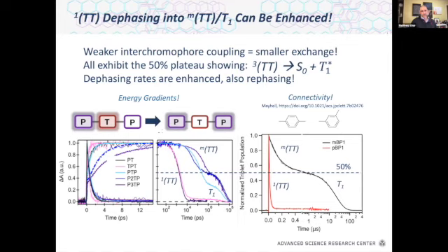But if you just deuterate the crap out of everything. Yeah, we tried with the deuteration. The easy ones to deuterate, I think, are on the TIPS groups, and it doesn't have an effect. I have to look up and see if we deuterated the backbone, but we did some preliminary results. We saw no change in the rates. But we didn't do every molecule. It was before we really understood everything, and so we tended to do the molecules where 1TT dominates, and so it's possible it's just the timescales aren't there. So it's probably worth revisiting.